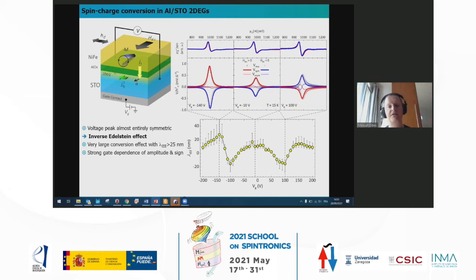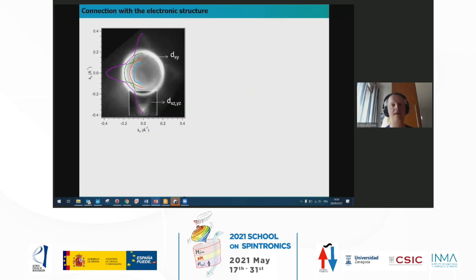So we have positive effect, change of sign, and then the negative maximum, negative minimum, and we were stopping here. Here, because we start with a higher current density, we are able to probe this additional regime. And also importantly, here we have a lambda which is larger, up to maybe 25 nanometers. So why does this inverse Edelstein effect change its sign?